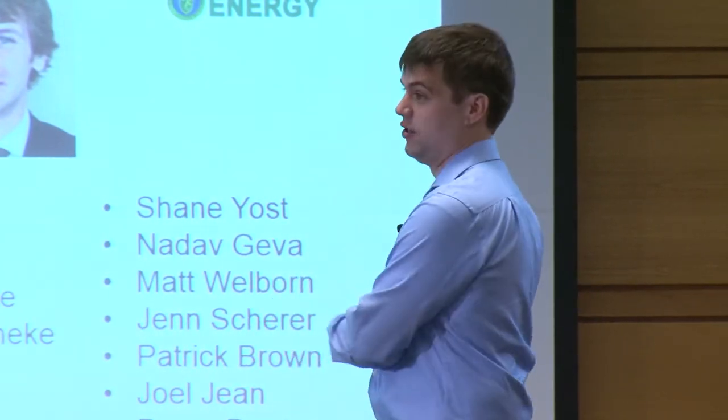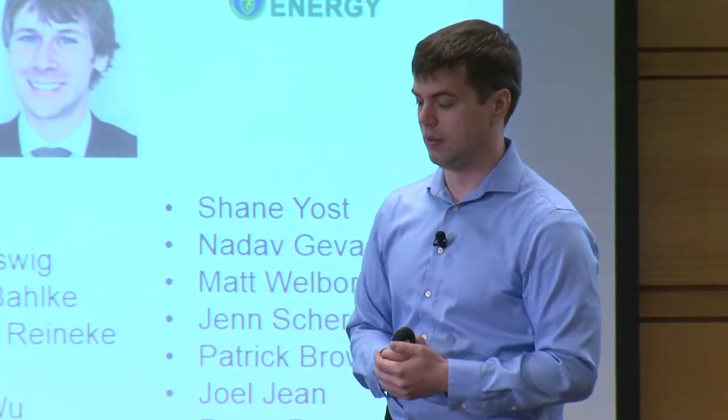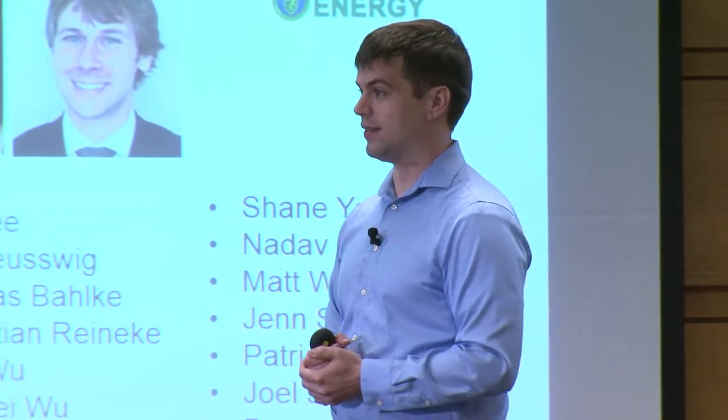But the challenge is that you need to get the thing you're sending the energy into extremely close to the nanocrystal, within 5 or 6 nanometers. That's proven to be the challenge. If, for example, we want to put this energy into silicon, we have to stick it right at the surface of the silicon for this to work with any efficiency. So those are really the two paths forward. We can try to take advantage of FRET, or we can hope that the quantum dot fluorescence goes higher. And actually, we're going to do both.